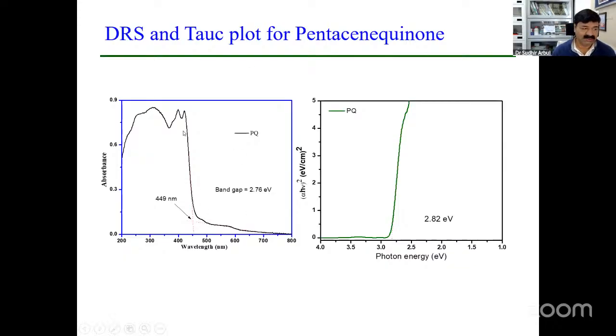Then we have converted this absorbance into a Tauc plot. Tauc plot means alpha h nu squared versus photon energy in eV. If you convert this whole axis using 1240 divided by the wavelength, you will get values in electron volts. Alpha means your absorbance, h nu means this. You can develop this in Excel also; you have to put in the formula. You will get alpha h nu squared versus energy in eV. Just plot the tangent, and you will get the exact value of your band gap. See here, from the direct estimate we are getting 2.76, and from the Tauc plot we are getting 2.82. This is more authentic and near to the theoretical band gap.